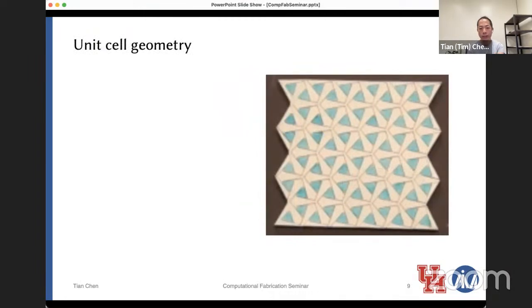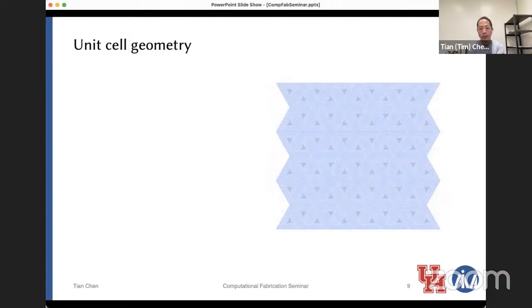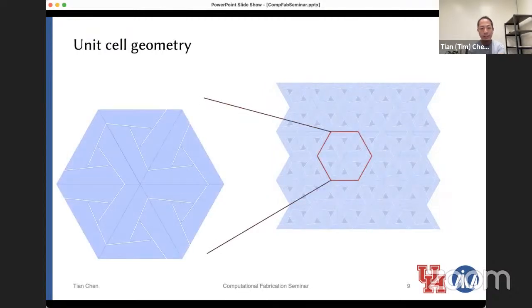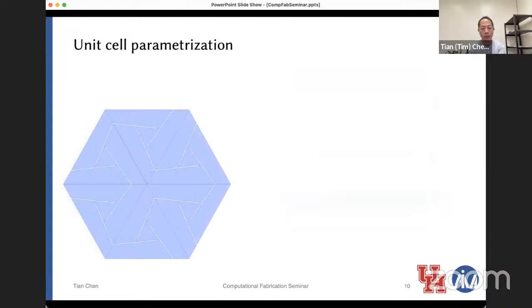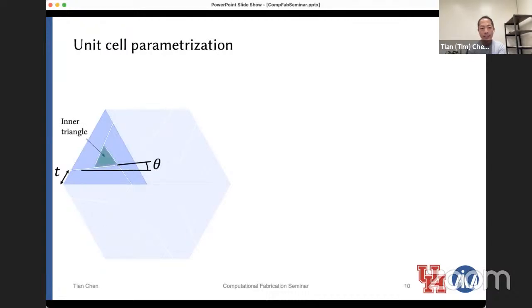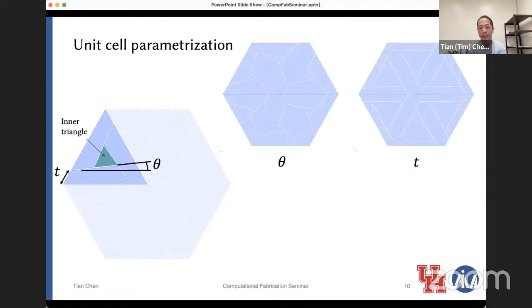So let's look at the unit cell geometry of the actual cutting pattern. We can abstract this into a hexagon featuring 6 mirroring triangular elements with these cuts. Focusing on the triangle, we can parameterize the geometry using T and theta. And then we look at the rotation of the inner triangle to establish the deployment. By changing theta, you're actually changing the orientation of the cut line, therefore making the inner triangle smaller and smaller. And changing T does exactly the same thing. Just by intuition, you can see that the smaller the triangle is, the less expansion we're able to get.